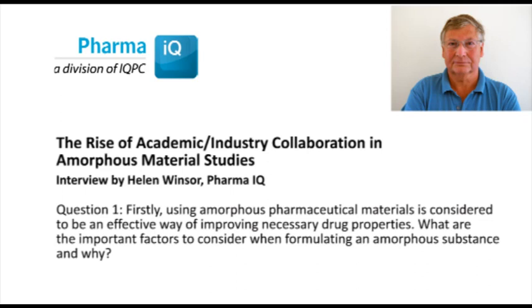So the nature of the glassy pharmaceuticals depends on sample history: the rate of quenching, of drying, of shearing, as is the case when you prepare amorphous compounds by spray drying, by extrusion, etc. So the issue is to manipulate the glassy state, to make it as stable as possible, physically but also chemically, while keeping solubility as high as possible. So it is necessary most often to formulate the API with excipients to increase the Tg, for example. The problem of solubility of API in polymer is a fundamental question.